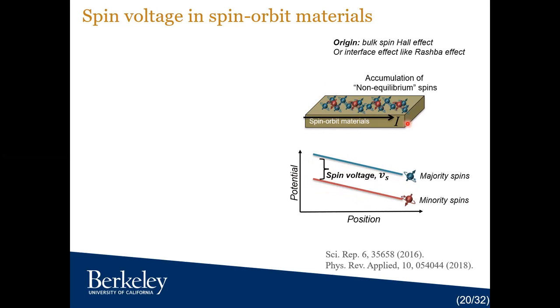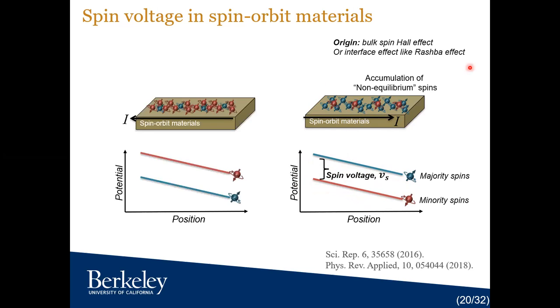constant across your material. And if you reverse your current direction, you just change the majority spin type, right? So that's why now your red curve is higher than the blue curve when you reverse your current direction. And that's why you can inject different types of spins into your MTJ for switching and create this new type of MRAM. So one interesting thing: since these are potentials, we should be able to measure them, right?